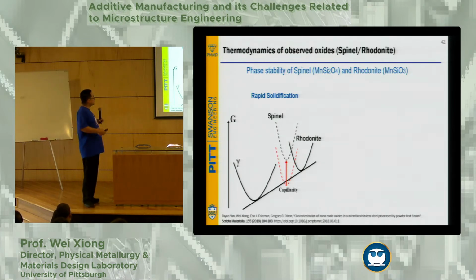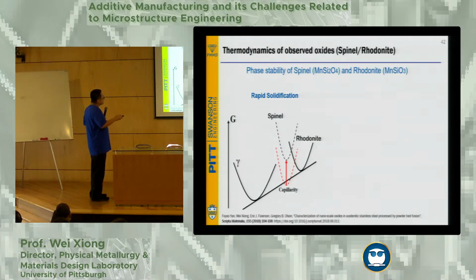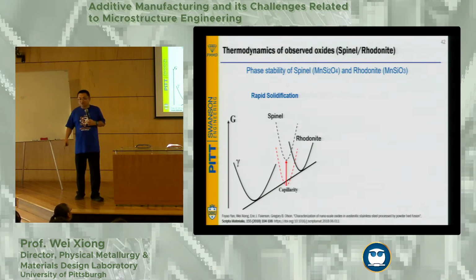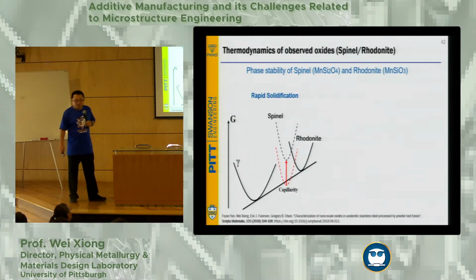So we were trying to understand. Our hypothesis is this is related to the Gibbs energy regarding the capillarity effects, the size effects. In the beginning, you have a very small size of this oxide particle, and rhodonite starts showing up with this interface energy. Therefore, it becomes equilibrium with gamma, the austenite phase.